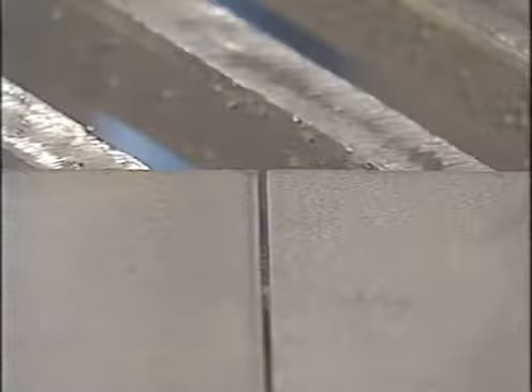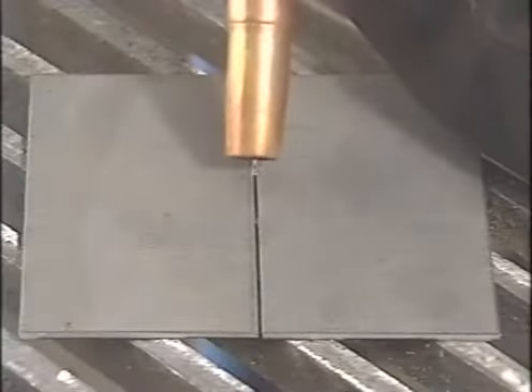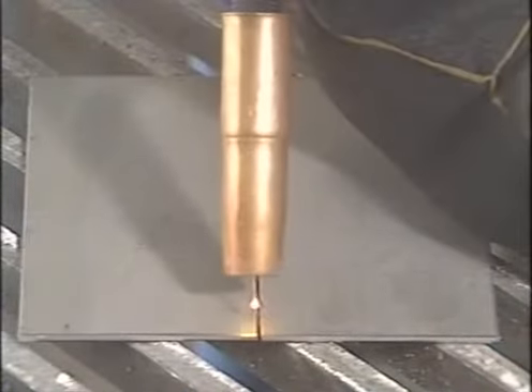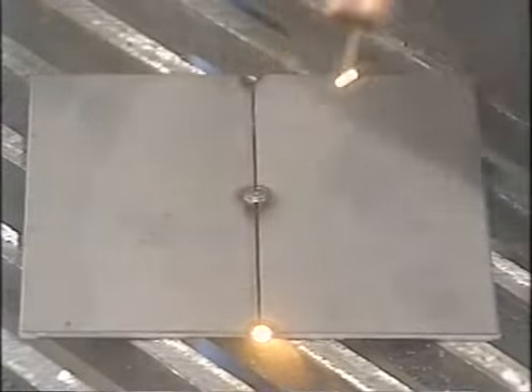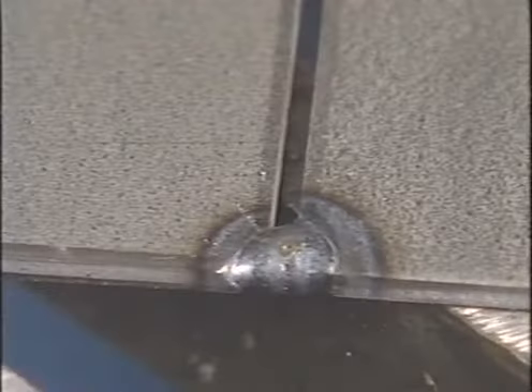The two pieces of plate should be placed approximately 1.5 millimeters apart to ensure penetration. Prior to welding, tack welds spaced at appropriate intervals should be used to maintain alignment. Small tacks should be used to ensure that they do not affect the appearance of the weld.